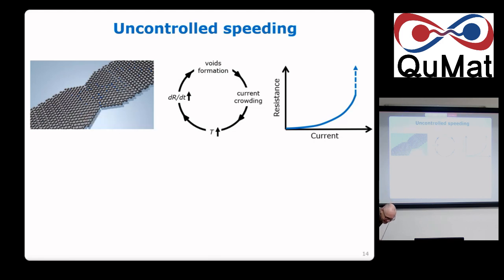So basically you start applying a current. The idea is the following: it's the electrons moving. You heat up locally, and then you start moving the atoms, and then you can make a constriction of the size you want. Okay, that's the trick. There is a problem here. The problem is that once you start forming voids here, the current crowding or the current density goes up, the temperature goes up, the resistance increases with temperature because it has a positive coefficient. Okay, it's a metal. Then you generate more heat, and this is a positive feedback loop. So you end up, without willing it, blowing your sample.